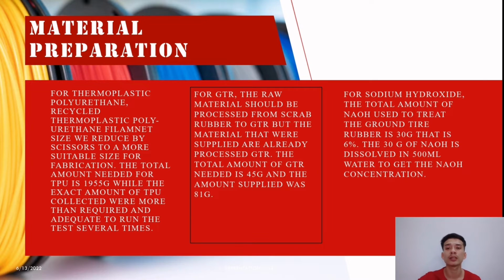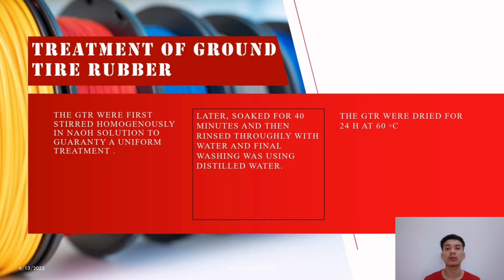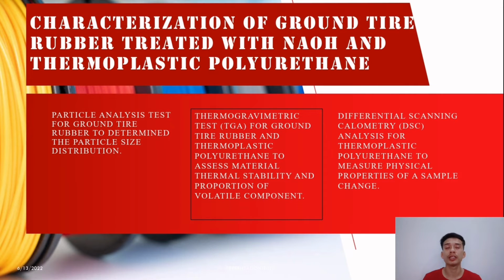500 ml water. Ground tire rubber was first stirred in the sodium hydroxide solution, soaked for 40 minutes, rinsed thoroughly with water, and given a final wash with distilled water. Then, the ground tire rubber was dried for 24 hours at 60 degrees Celsius. After treating the GTR, we proceed with characterization of the ground tire rubber treated with sodium hydroxide and the thermoplastic polyurethane. First, particle analysis for GTR to determine the particle size distribution. Second, thermogravimetric analysis for GTR and TPU to assess the material thermal stability and proportion of volatile components. Lastly, differential scanning calorimetry analysis for thermoplastic polyurethane to measure changes in physical properties of a sample.